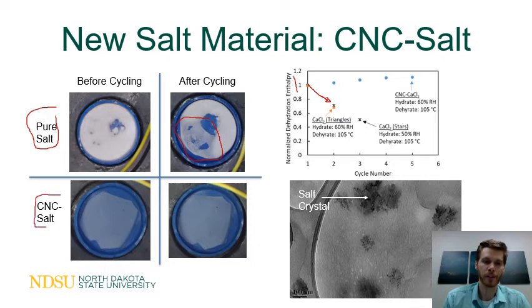But we have introduced this new CNC, which is cellulose nanocrystals, into the salt, and that provides a structure for the salt. This SEM image down here shows the black area as salt crystals, and the really faint lines are cellulose nanocrystals going through it. Those provide structure and keep the salt crystals apart, so that when we look at it before and after cycling, it looks exactly the same, and our energy is also relatively stable. That's a very good thing, that we can provide stability for the salt through the cellulose nanocrystals.